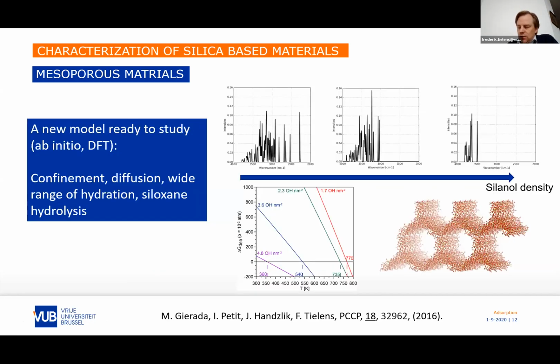After that, we calculated a vibrational spectrum, also with the aim to compare and to have some fingerprints to see what is the effect of water in these kinds of systems, and also some thermodynamic structure. I will go on, especially on the thermodynamic calculations, in the next part. I will present all the diagrams like this. So what we did here is that we built different structures with different hydroxyl densities, and we estimated the stability as a function of the temperature.